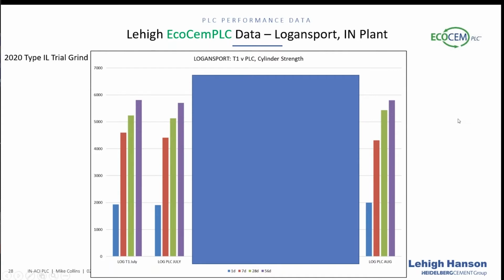So I know that there are some of you guys that rarely would use just an OPC mix. So what happens when we look at fly ash? We took a fly ash that would be common in the northern part of the state, and we mixed that with the Logansport Type 1, and we also mixed it with the Logansport PLC ground in July. And again, like for like or better, very equivalent strength performance. We also did a mix with slag and those same two cements. And again, the story is the same, a little bit better at 1 day and pretty equivalent as we go up in 7, 28, and 56 days.